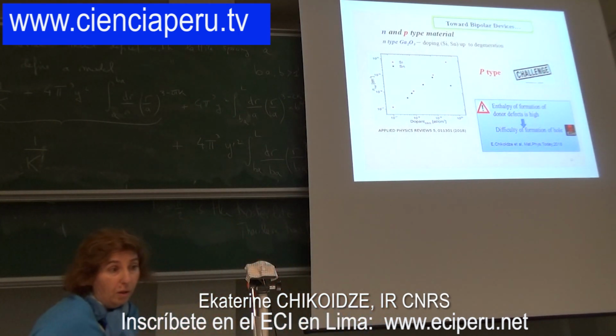So gallium oxide, of course, is an oxide and has the same problem as other oxides. It is very well doped, easily doped to be n-type, but the challenge is p-type. But as I said, there is a good surprise. We had a theoretical estimation, and we found that the enthalpy of formation of donor defects is very low, if we compare, for example, with zinc oxide, which has a permanent problem of p-typing. And this theoretical